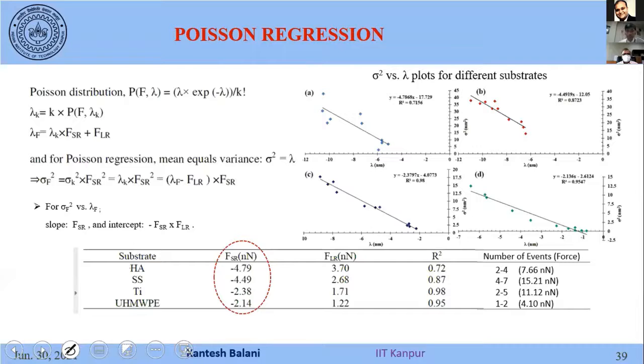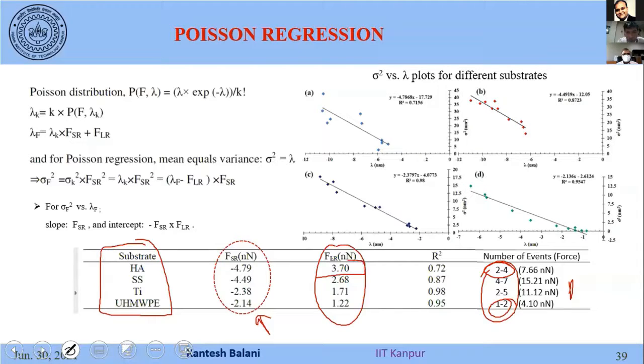Then once we get these plots of different peak forces, we translate them and see what the long range forces are using Poisson's regression and what the short range forces are. And that will tell us the number of events that might be happening on that particular substrate, that particular protein. So we can see only 1 or 2 events might be happening in protein, but 2 to 4 events might be happening in hydroxyapatite, ceramic, and metals. It is much larger. Not only that, hydroxyapatite has the strongest long range force, strongest short range force. So it is a bioactive material.